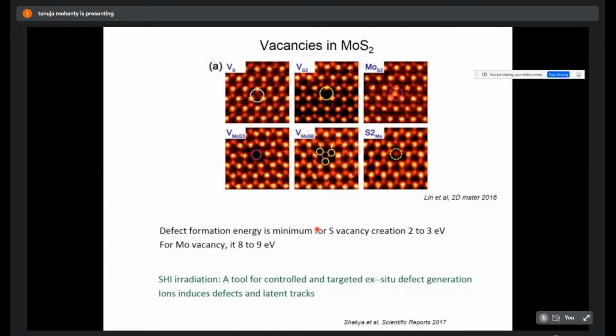We are doing this swift ion irradiation, which is a tool for controlled and targeted ex situ defect generation. Ions induce defects and latent tracks. One thing I have not told you is the latent track. That word is not normally used when people study only defects, but people used to ion irradiation studies use latent tracks. Latent tracks means a successive series of defects, or line defects in a line, for a long period. The length is much higher than the width of the defects, so it is like a track, a pipe of defects, but normally it has a conical shape. Swift ion irradiation can do those things.